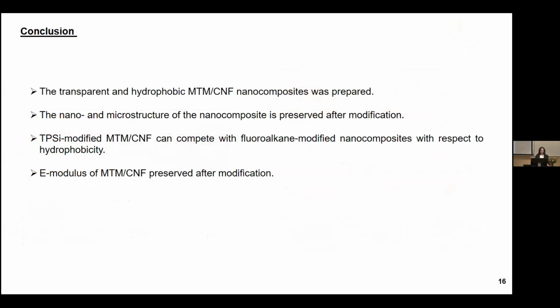The conclusion of this paper is that we could prepare a transparent and hydrophobic MTM-CNF nanocomposite. The nano and micro structure of the nanocomposite is preserved after modification, and the MTM-CNF modified with the mercapto group can compete with the fluoroalkyl modified nanocomposite with respect to hydrophobicity, and the E modulus of MTM-CNF is preserved after modification.